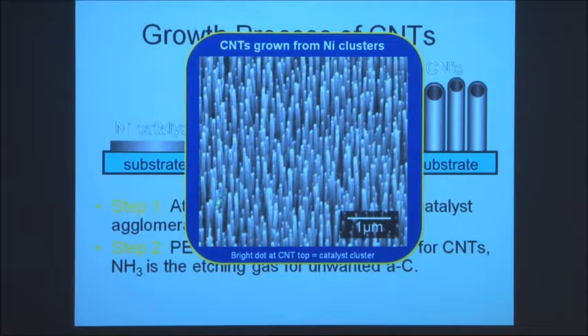So you can see what we've got is a bunch of carbon nanotubes growing upwards from the substrate, as shown here. And the nickel, as you can see from the little white dot, is at the top. So this is what's called a top-down process, where the nickel catalyst grows up the way, and below it, the nanotubes grow, pushing the nickel up from the substrate. These are multi-wall nanotubes. You can see we can now grow them in a particular direction. So that's one thing we said we wanted to do. We want to be able to control the direction in which they grow.